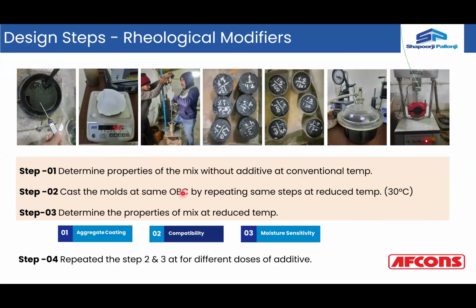Okay, you need to work on your warm mix temperature based on your conventional hot mix temperature, because the same mix is getting converted into warm mix by adding additives in the binder. So VG40, if added with Evotherm, can be converted into warm mix, and then in that particular case, if you are adding that in your lab, your mix temperature should be reduced by 30 degrees centigrade, and then determine the properties of the mix at that reduced temperature, like aggregate coating, compatibility test, and then the moisture sensitivity test.